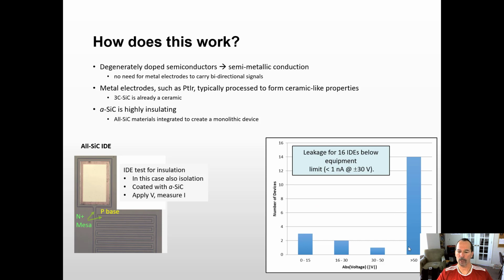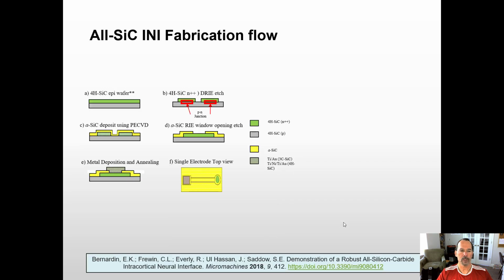And looking at the histogram, again, we see a majority of our devices, 14 of them, didn't leak even a nanoamp up to plus or minus 50 volts. We had one device that went out to 30, and the rest were basically leaking more current down here. But in every case, it was more than 6 to 10 volts before we measured 1 nanoamp of leakage current. So quite impressive.